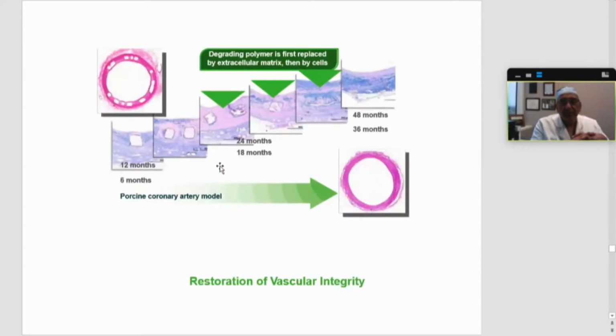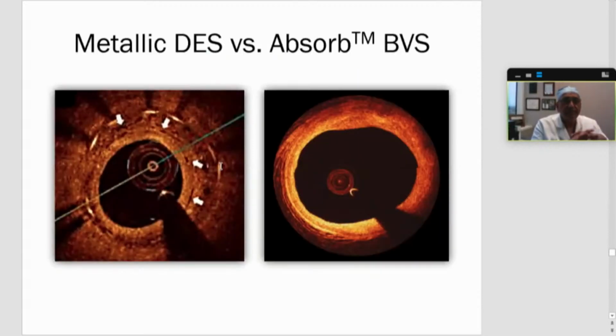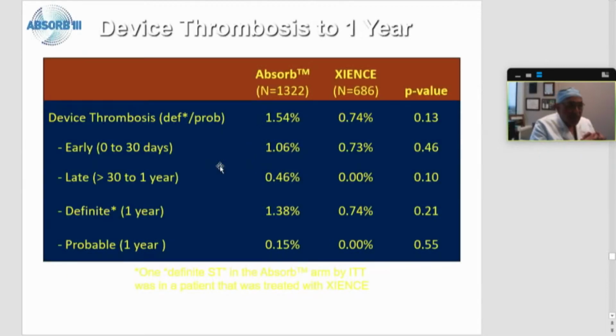And then the vascular integrity is restored by deposits of extracellular matrix, and then eventually by cells in those absorbed segments of the BVS. And this is what it should look like. This is the ideal golden tube. You basically have a metallic DES on the left side with neointimal proliferation versus Absorb, where you hardly have any further narrowing left. However, when we went into the trial phase, the reason this technology is not in prime time is because we are working on the next generation, and the biggest reason was stent thrombosis. Stent thrombosis rates were about 1.54% in the Absorb arm versus 0.7%, so almost twice the number that we would accept, so to speak.